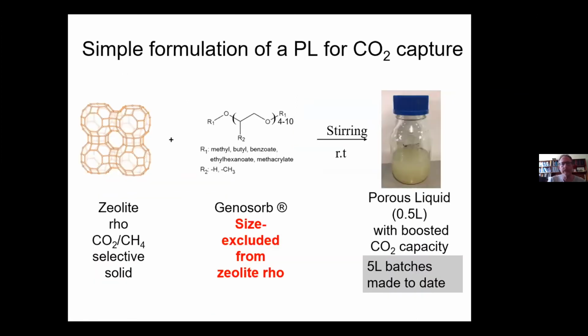And that's exactly what we did. So it boils down to something very simple. These are the polyethers that are already used for CO2 capture, trade name Genosorb or Selexol. This is a zeolite rho, which is known in the literature to have high CO2 capacity and high selectivity to CO2 over methane. And because the pores are very small, these ethers cannot fit inside.